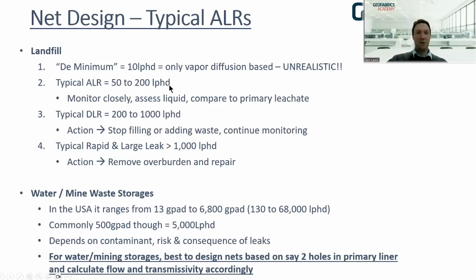Otherwise, 50 to 200 litres per hectare per day is quite common for an action leakage rate. For a design leakage rate, maybe that's the point at which they have to take action. It's a bit confusing actually, but at the ALR, you maybe monitor it closely and assess liquid compared to primary leachate. Otherwise, you can set a higher leak rate for when you have to take action and stop filling, maybe start thinking about continued monitoring or stop adding in waste or water.